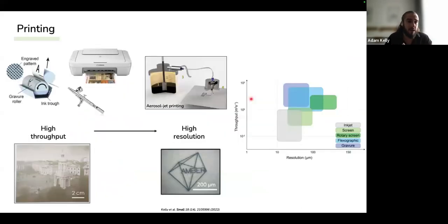So we have these inks. This is great. Now we have our material. How do we deposit them then? Well, we have high throughput methods like the roll-to-roll flexographic methods, which allow us to produce high areas. Generally, the resolution of these tends to be a bit lower than what we can achieve with something like aerosol jet printing, where we can get extremely fine feature sizes, but the cost of that is obviously a very small nozzle, so you pay the price then with your throughput. So we need to decide what the trade-off is.